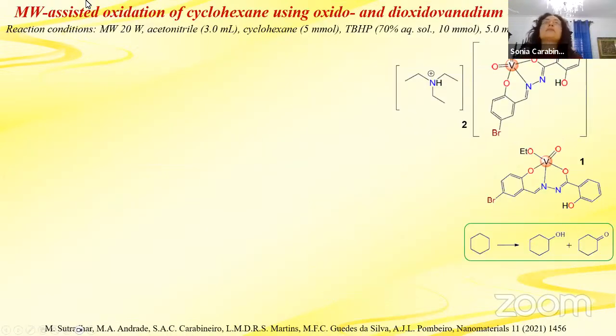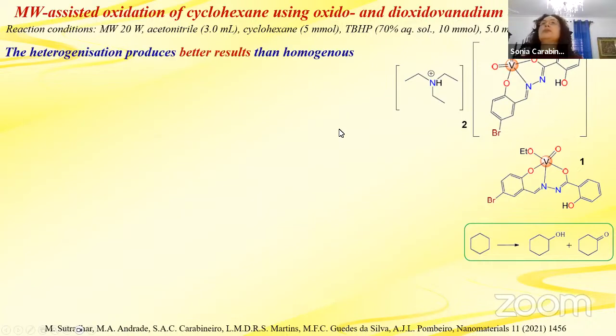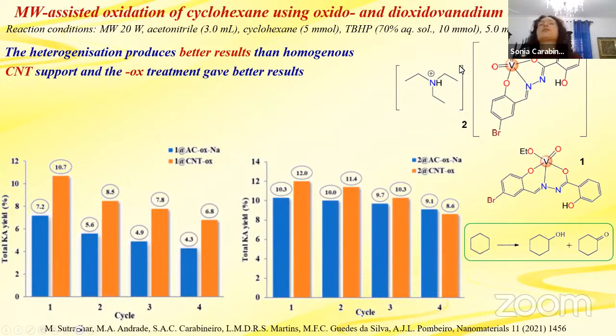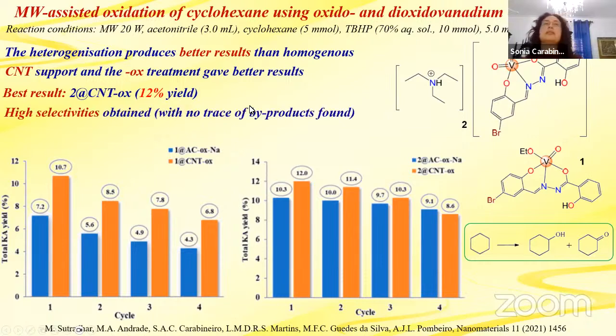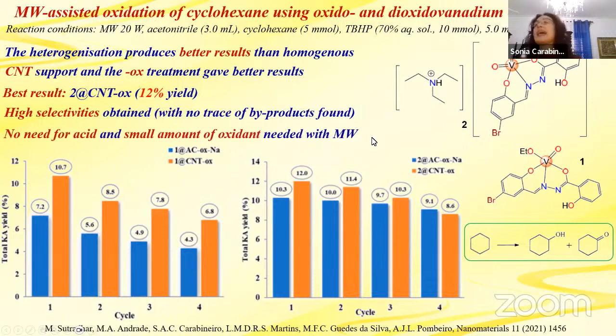We also tested the microwave-assisted oxidation of cyclohexane using these oxido and dioxido vanadium complexes. And again, we saw that heterogenization produced better results than homogeneous for this reaction. And the carbon nanotubes and the oxidation treatment gave better results. We have them here, for complex 1 and complex 2, and the best result was 12% yield. Remember, in this reaction the industrial process gives only 4 to 12%. So it was similar to the industrial one, but at lower temperatures than they use. Again, high selectivity and no need for acids. We used microwave and only a small amount of oxidant was needed.